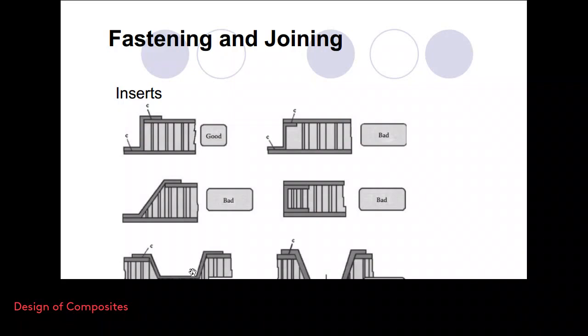So you may have such a design. In fact, what we see is we have a metal part on either side. Possibly this may be done for the joint. In fact, we see that the struts of the honeycomb structure under the channel are buckled. So basically this means that they cannot deform more. Possibly they have a plastic, permanent deformation, and in fact when you apply a force from either side, it will not debond easily.